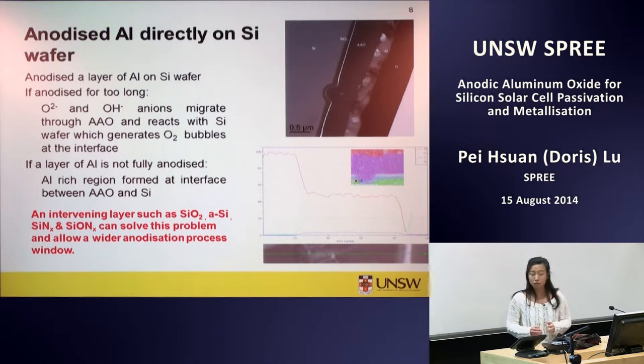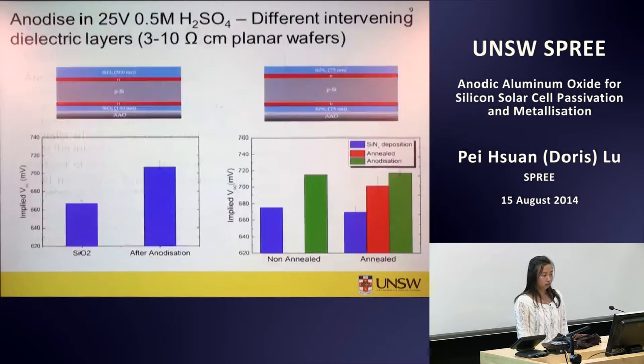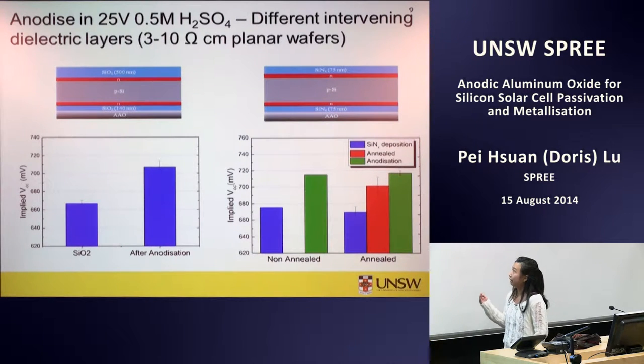That leads to a conclusion. We need an intervening layer to stop the aluminium from continuing to anodize into the silicon wafer. So later we started putting in an intervening layer such as silicon dioxide or silicon nitride.